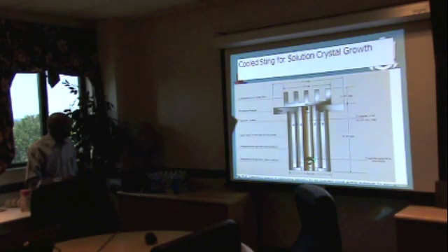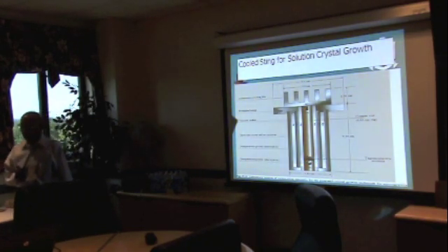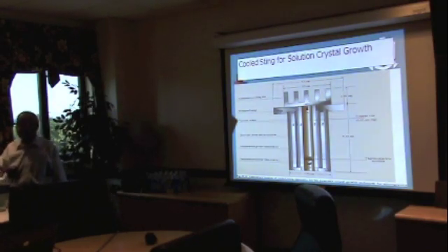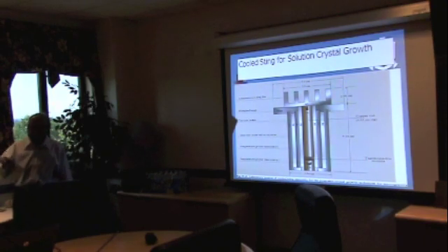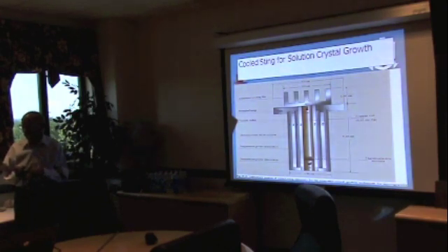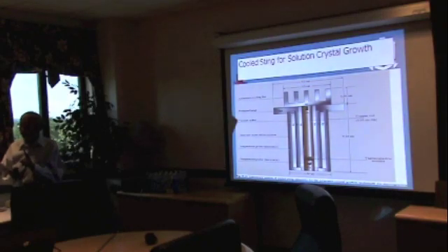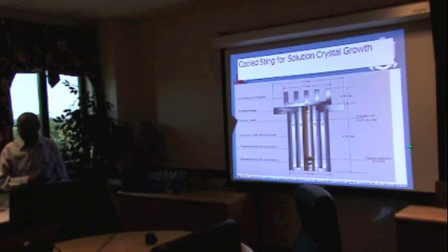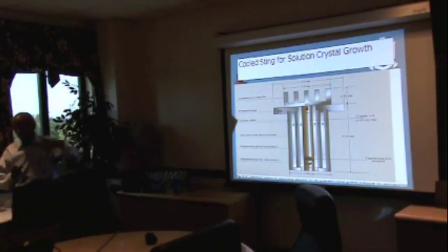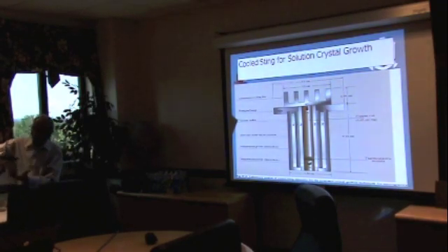So one thing learned from this series of experiments is that the transition from dissolution to growth is very, very uniform in a space environment. On the ground, it is very abrupt because gravity helps to change the current temperature very easily. So on the ground, it is very abrupt, and that's why the crystal always has defects. But in space it is very uniform. So we change the temperature, we dissolve the seed crystal, and then change the direction of the current.